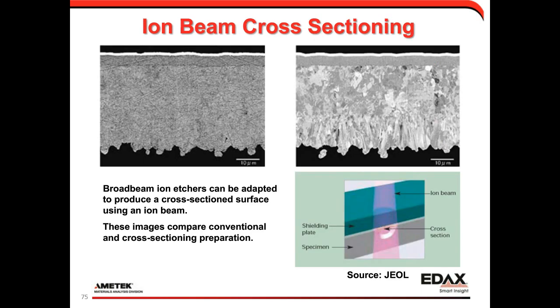And then in addition to using this for surfaces, we can also do cross-sectioning. So this is an example from the JEOL cross-sectional polisher where the ion beam can go straight down against the surface. It's blocked using a shielding plate, so it goes in basically perpendicular to the sample surface of interest.